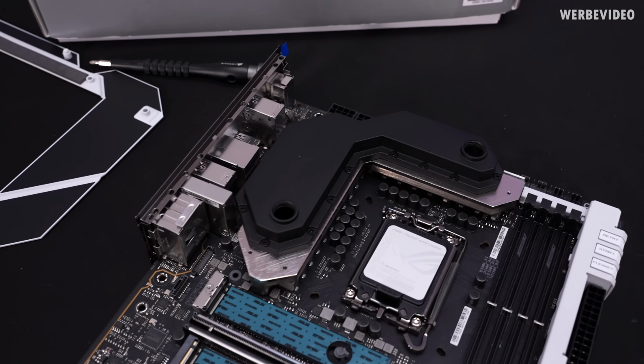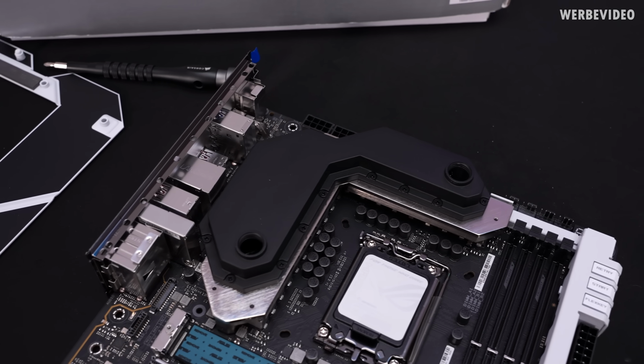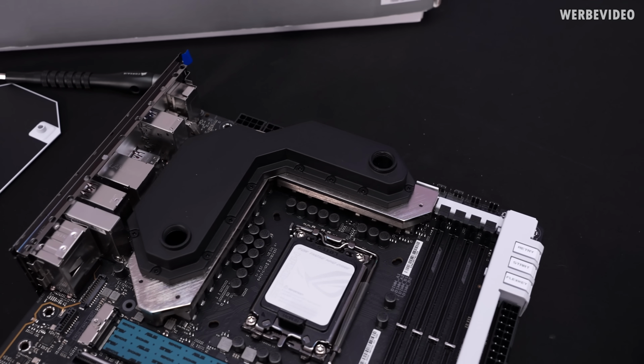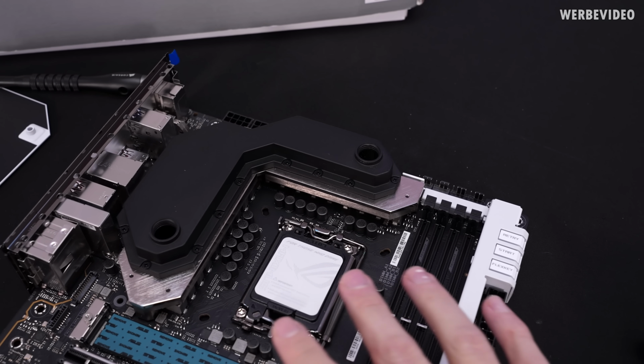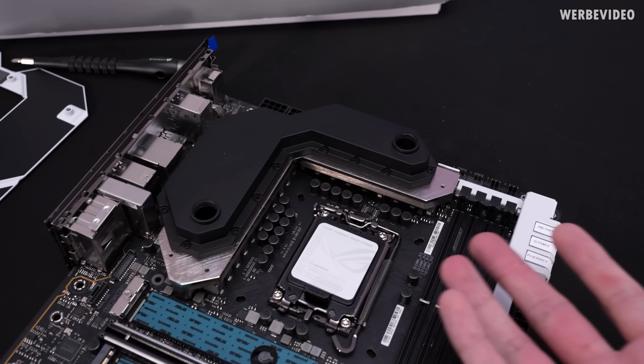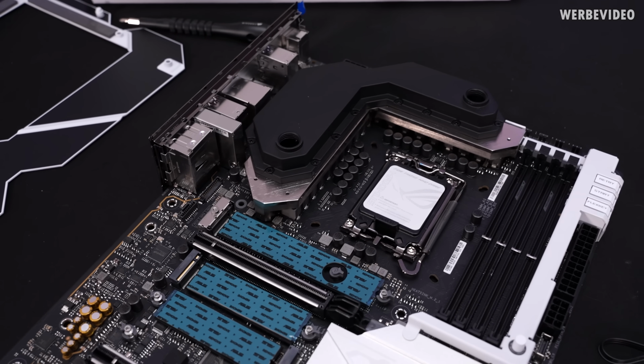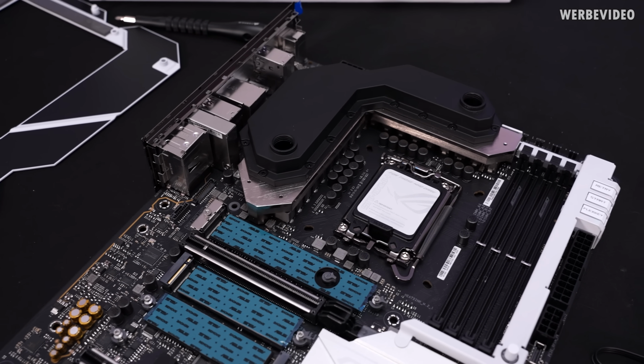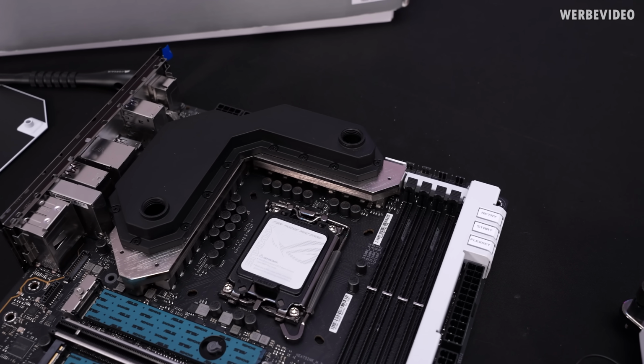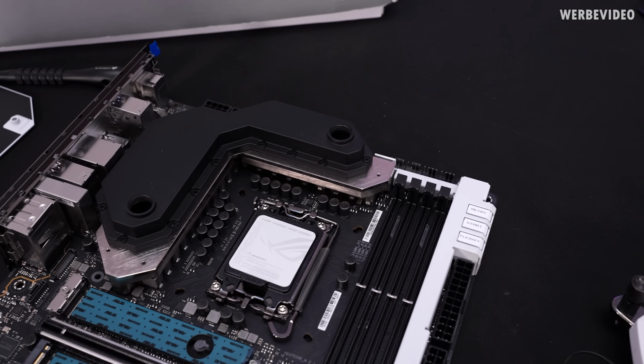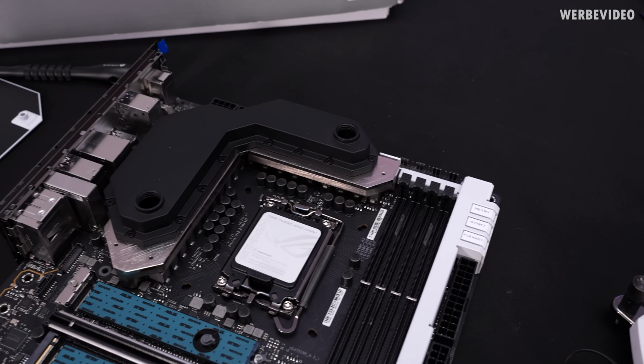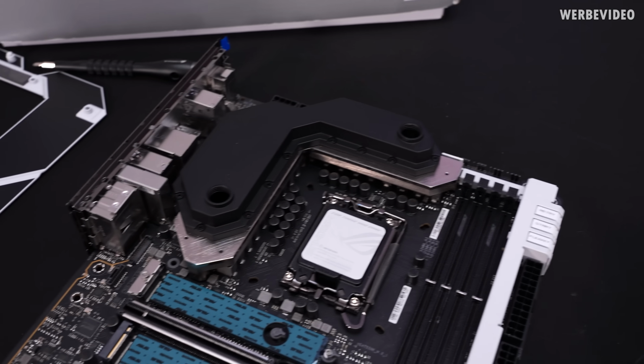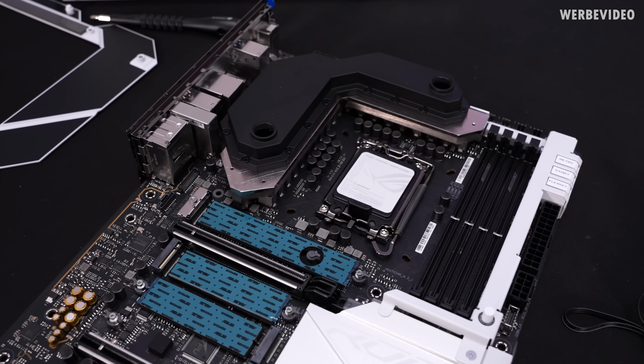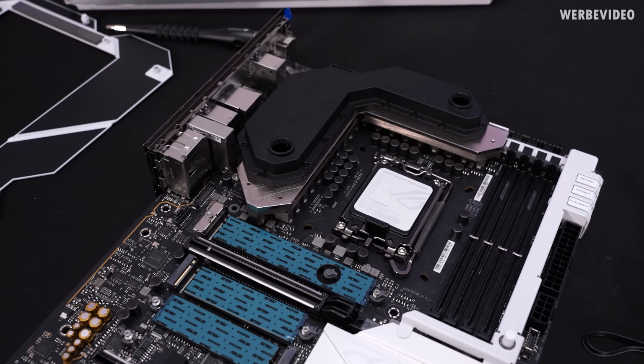And here we have the VRM heatsink. And we already tested this with Z690, because if you look at this, it's mainly made for water cooling, because it doesn't really have a ton of surface area. So you would assume that air cooling might not work as well. But we tested this with the Z690 and it worked surprisingly well, which is mainly because I think the VRM is just very efficient, and thus the heat generated is just not that much.